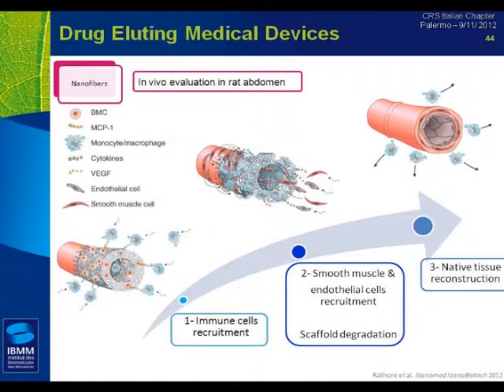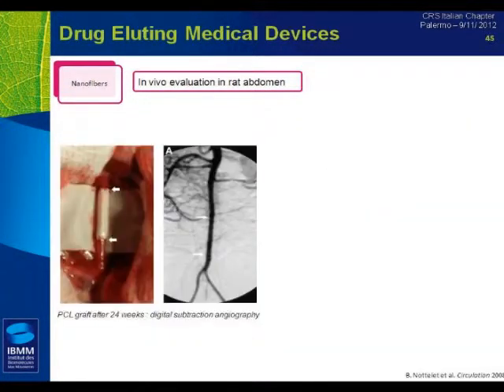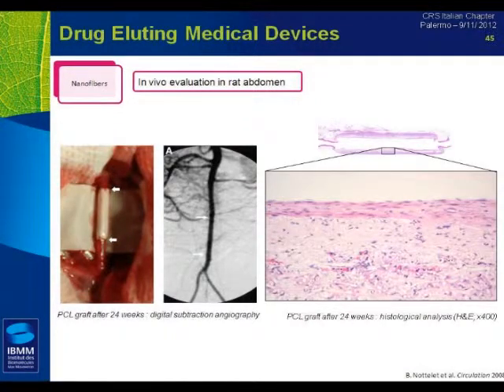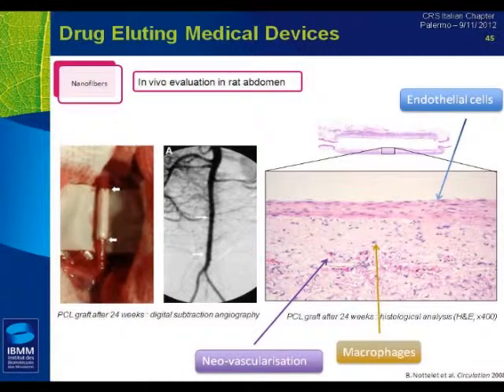So we looked at this by implantation on the abdominal aorta of rats. And you can see here the graft in the aorta. And after 24 weeks, you've got here an example of histological cut. And what you've got here is the luminal part, the internal part of the graft. That's the wall of the graft. And you can see appearing neovascularization to provide nutriments, macrophages as expected, and also endothelialization, which comes as soon as 3 weeks after implantation. You've got full coverage of those systems.